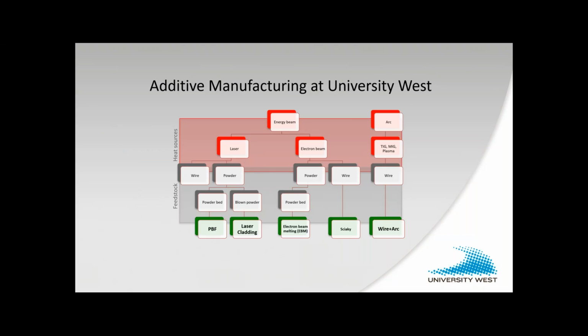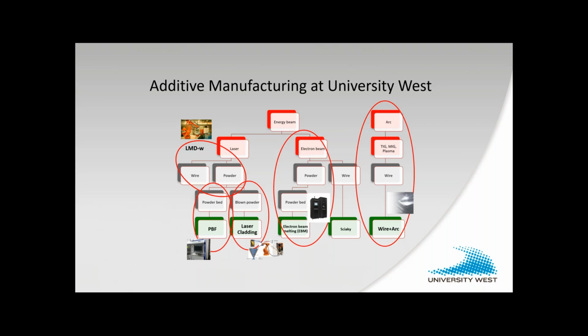The AM processes at University West are basically what you see here. We do a fair amount of laser metal deposition using wire as feedstock, but we also do it with powder as feedstock, the blown powder process, and together with others, we have a fair amount of projects on powder bed fusion based on the laser source. Then we have an in-house system for electron beam powder bed fusion, an A2X machine from Arcam, and we also do wire arc additive manufacturing, not least together with ESAB in Gothenburg.